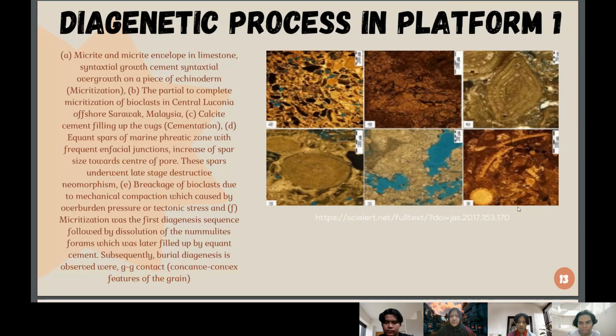So finally, we move to the diagenetic processes in platform 1. Based on the diagram, it can be interpreted that the aggrading neomorphism was found, where the huge majority of the microcrystalline calcite samples are recrystallized to sparry calcite with different ranges of crystal size. The components go through different processes, from complete to partial aggregation of recrystallization. This process builds up the shell of the skeletal components to a stable phase, supported by the presence of high magnesium calcite under meteoric conditions.